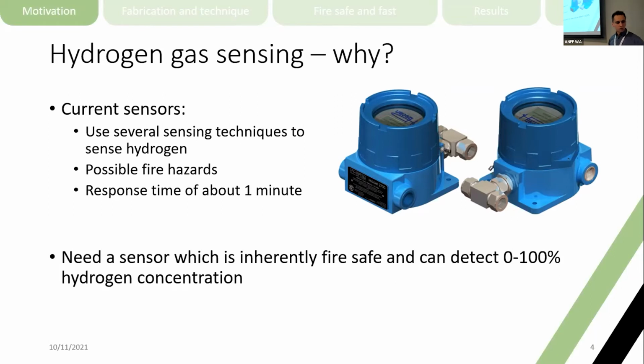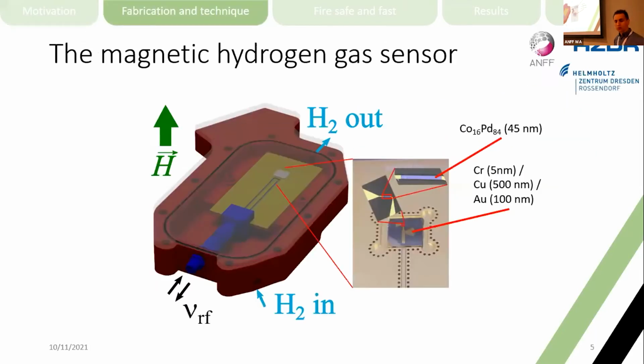And you see, for both those techniques, you apply a voltage in the hydrogen environment, and then there is a possible yet small fire hazard. And also, these sensors have a typical response time of about 1 minute, and we just think that could be faster. What we would need is a sensor which is inherently fire safe and which can detect this broad hydrogen concentration range. Instead, I want to present to you the magnetic hydrogen gas sensor.